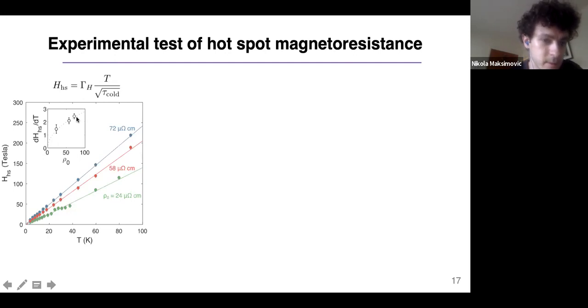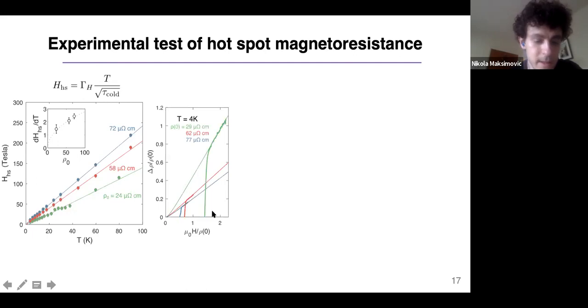It's not the most striking observation, but you can easily test using Kohler's rule whether the disorder scattering rate adds in a linear fashion with all the other sources of scattering. One of the assumptions of Kohler's rule is that scattering rates add linearly. And at 4 Kelvin, as we change the disorder level in our samples, there's a clear failure of Kohler's rule. So this strongly points to an anisotropic scattering mechanism.